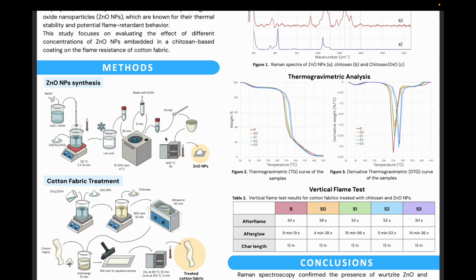Sodium hydroxide was dissolved in water and ethanol, and this solution was added drop by drop to a zinc acetate solution under stirring at 55 degrees Celsius for 2 hours and 15 minutes. The solution turned white and was allowed to cool to room temperature. It was then centrifuged at 15,000 revolutions per minute at 4 degrees Celsius for 35 minutes.